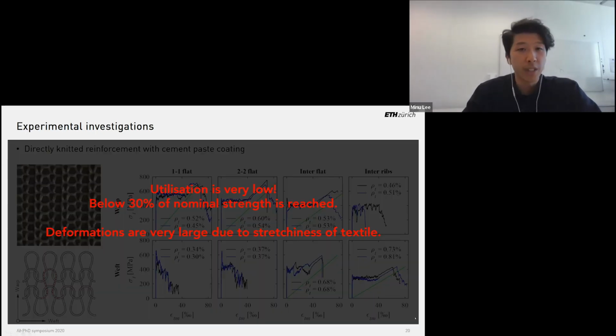Okay, so what we could see from these results is that generally the utilization of the textile strength when compared to the filament strength was very low, and not even 30% could be reached. This comes from the interlock structure of the knitted textiles, where the loops introduce high lateral stresses on the yarn, and which significantly reduce strength. Furthermore, the deformations were very large since the textile introduces a stretchiness which exhibits a stiffness that is a magnitude lower than the fiber material.